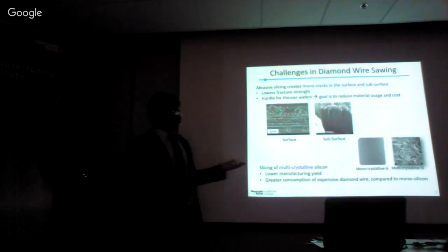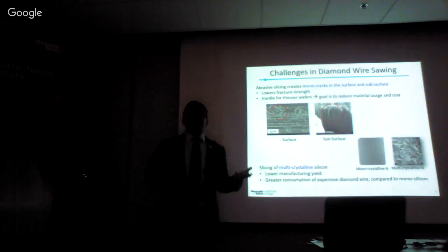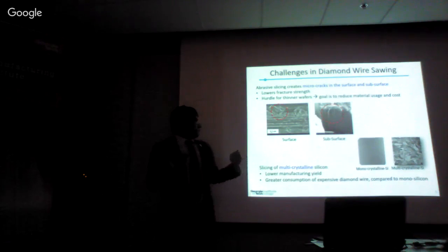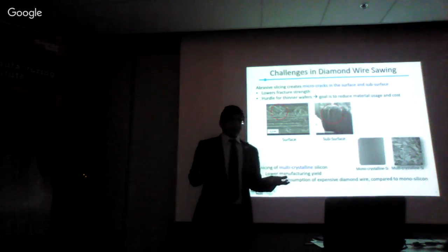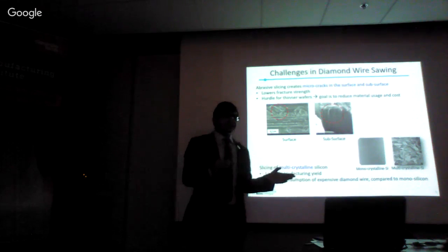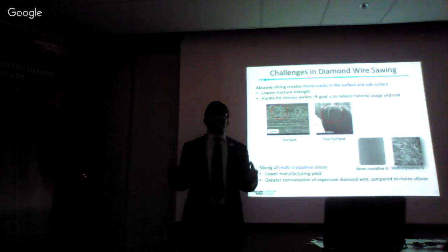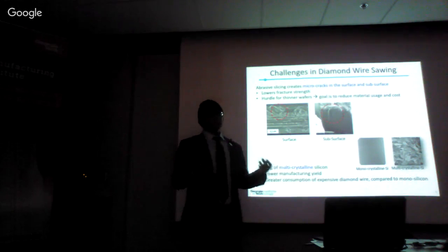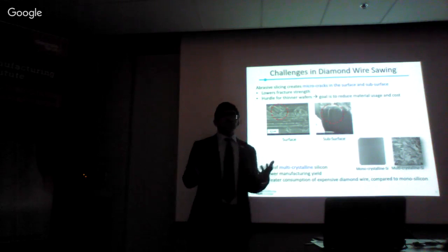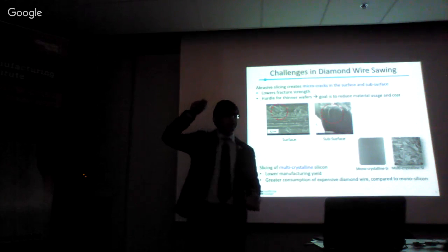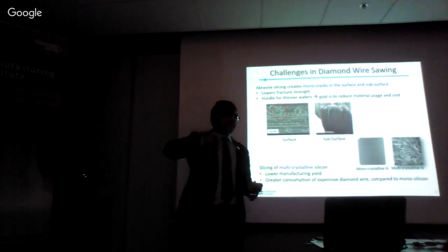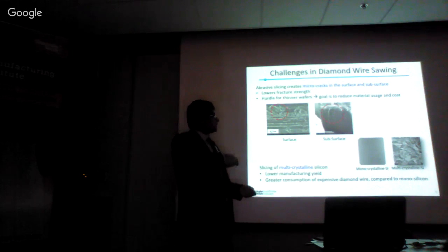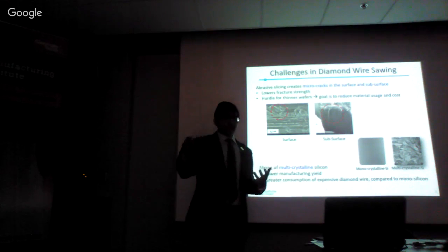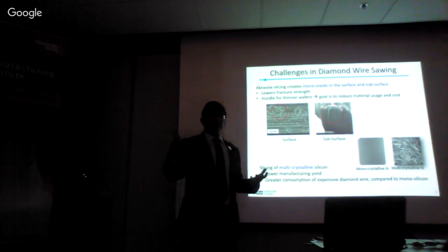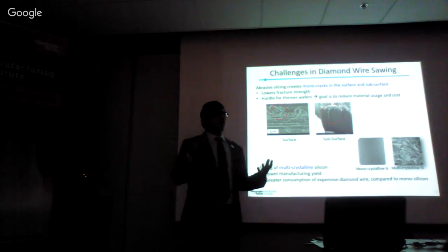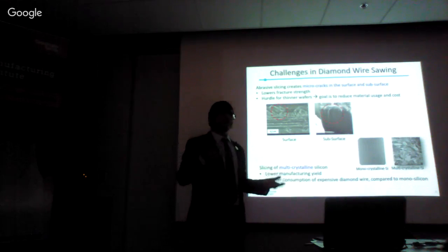The next challenge in diamond wire sawing of silicon wafers is cutting of multi-crystalline silicon. Now, compared to monocrystalline silicon, the cost of multi-crystalline silicon is much lower because it could be cast very easily, and does not require a very slow Czochralski process of pulling out a crystal from the melt. But multi-crystalline silicon is characterized by many grain boundaries, twin boundaries, inclusions, dislocations, and whatnot. Not a very pure material compared to monocrystalline silicon.